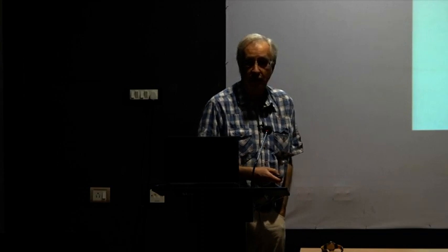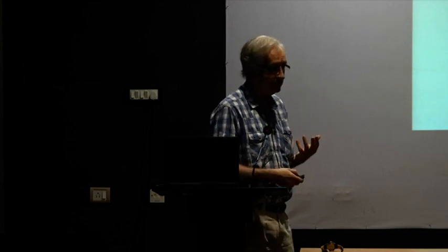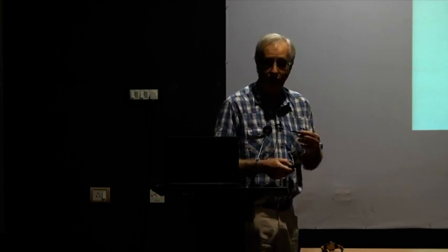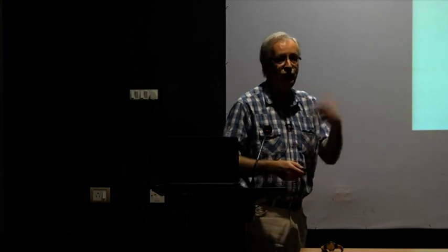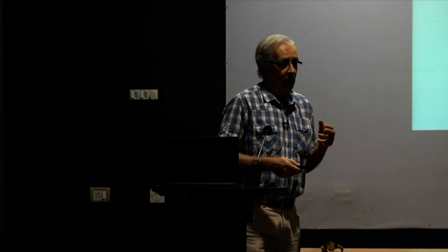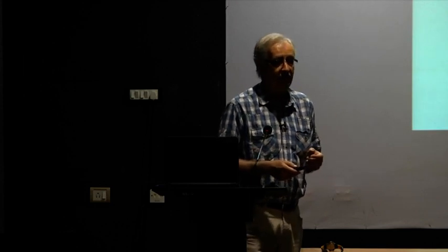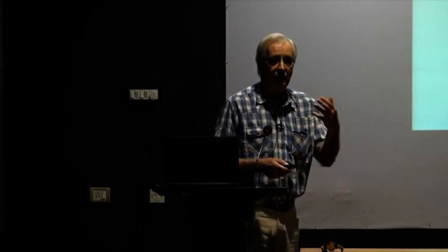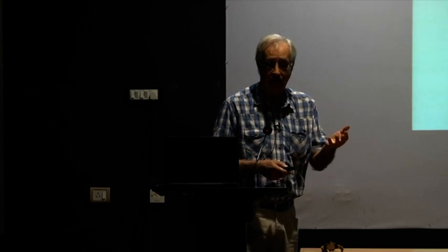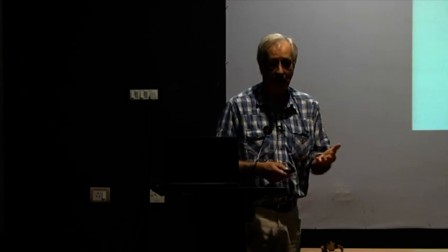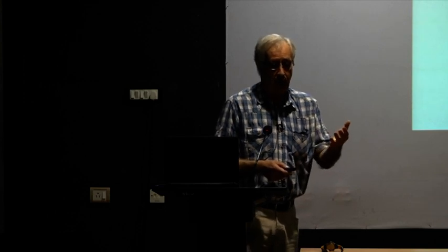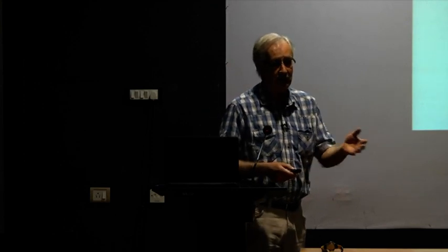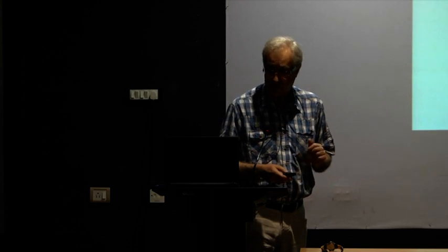Now, superelasticity has some other interesting things. You're going from one state to another state. So if you're going from one state to another state, you're changing the entropy. And if you're changing the entropy, then you may be extracting the latent heat of the system, because in the first order transition, there's a latent heat. And when you go through this transition, that latent heat has to be either supplied or extracted, depending on in which direction you're going.